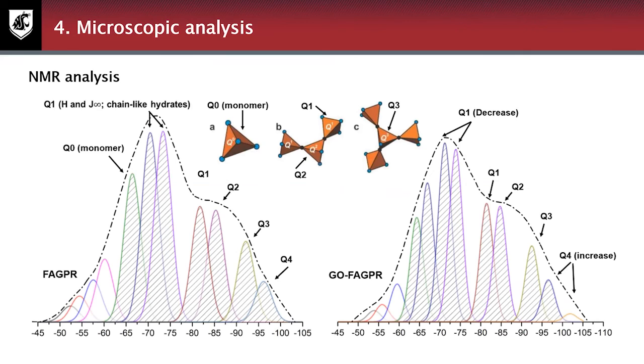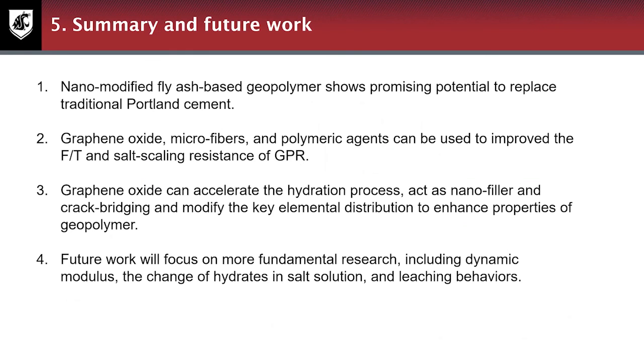Okay. Here is the NMR analysis. So based on the location of the silica oxygen tetrahedron, the basic unit can be classified into 5 groups. From this NMR analysis, after adding graphene oxide, the Q1 decreases and the Q4 increases. This means the hydration product was converted from simple formation to some more complex formation.